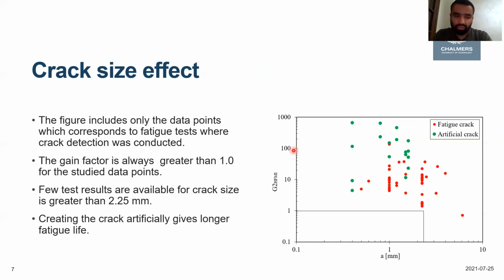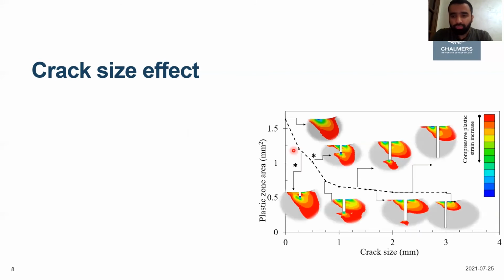That's much better. As I mentioned, almost 50% of the data pool contains no description of the fatigue crack size. So that requires another way of analyzing it, and this is what we do. This is what you will see in the coming slides. But here we need to understand why we get a high gain factor.